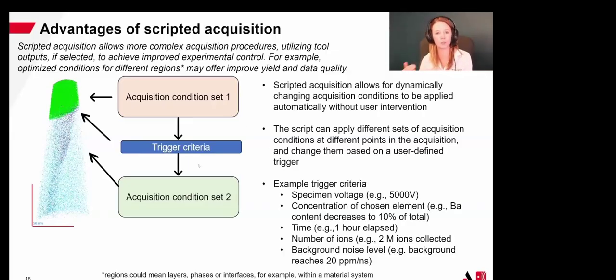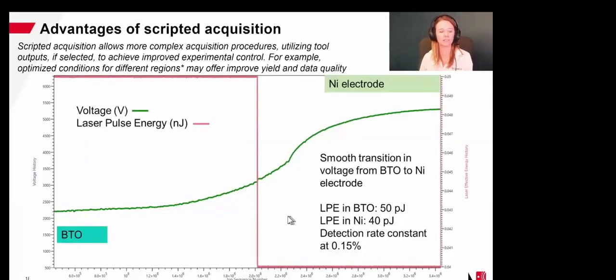And when we reach a trigger criteria, that could be something like a particular voltage. It could be the concentration of a certain element in our mass spectrum. So for example, when we see 2% barium in our mass spectrum, that can change our acquisition conditions to a second set of user-specified acquisition conditions. And this is going to help make sure that the conditions that we're using are appropriate for each different material type and increase the success rate of obtaining that interface. This can also help improve our data quality.